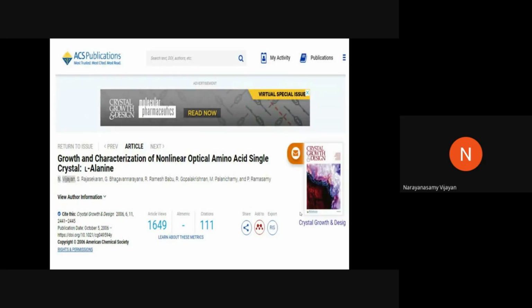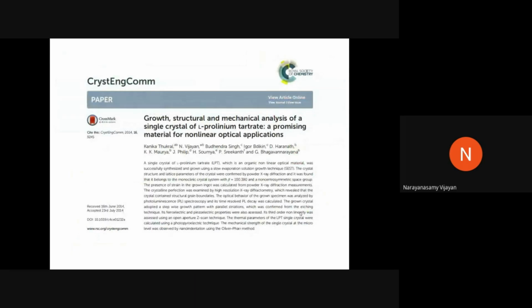And for L-alanine, as single crystal growers, we have varieties of techniques. Particularly for slow evaporation solution growth, we have slow evaporation or slow cooling. There is one more technique called the seed hanging technique. With the seed hanging technique, we have grown L-alanine, and the seed is held by some thread. How the thread influences the other parts of the single crystal, and how the defects increase, those analyses also we have done.